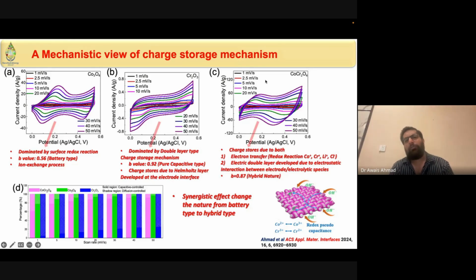And if we mix together, which was our material, chromium cobalt nanowires, it happened that it behaved as both capacitor and battery. So that's the reason we called it aqueous hybrid supercapacitor, which has the behavior of both side reactions. And in the end, we get a more synergetic effect, from battery type to hybrid type.